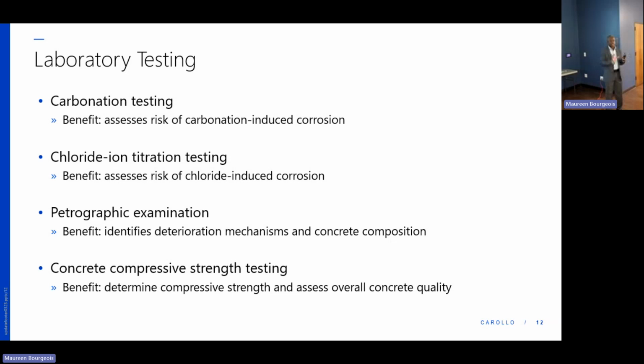The cement is typically alkaline. Opposite of alkaline is acidic, so it's not acidic. But the carbon dioxide reacts with it, breaks it down, and gets the concrete to go in an acidic direction. That is really not good for the reinforcing in the structure. So now it begins to deteriorate the concrete and then begins to deteriorate the reinforcing with the right amount of water and oxygen when they come in contact with it. So we want to measure that level within the structure. Because we know the concrete cover, we're able to do that.